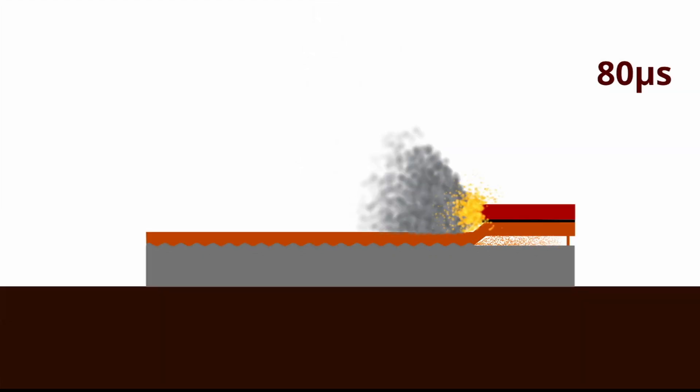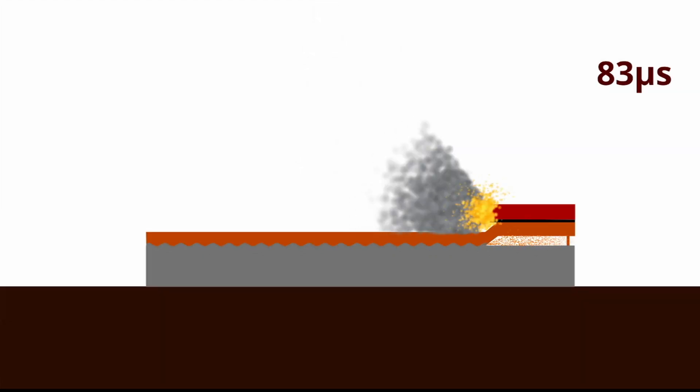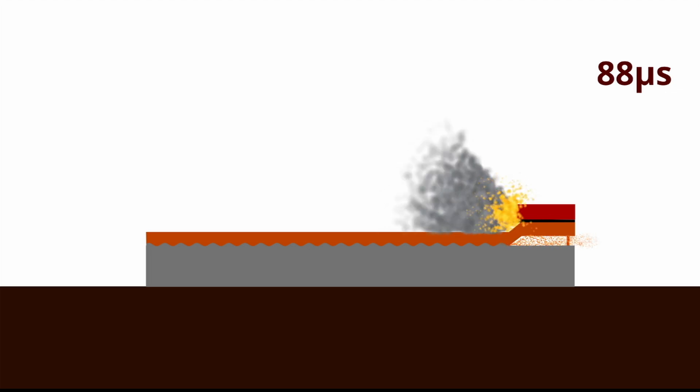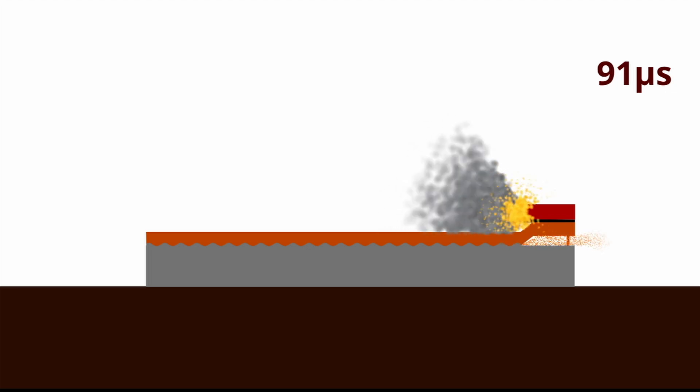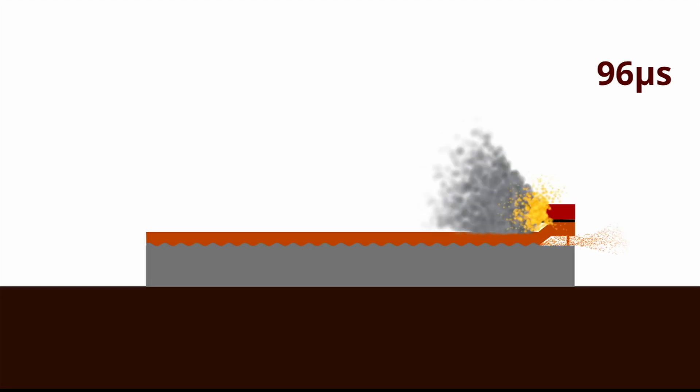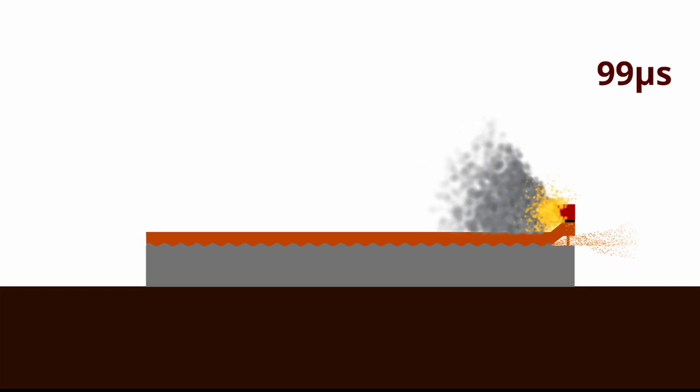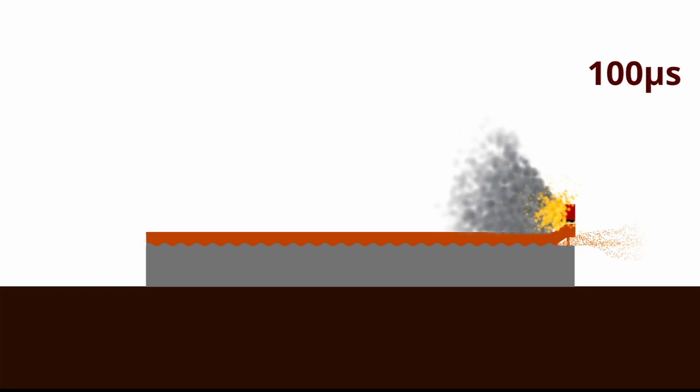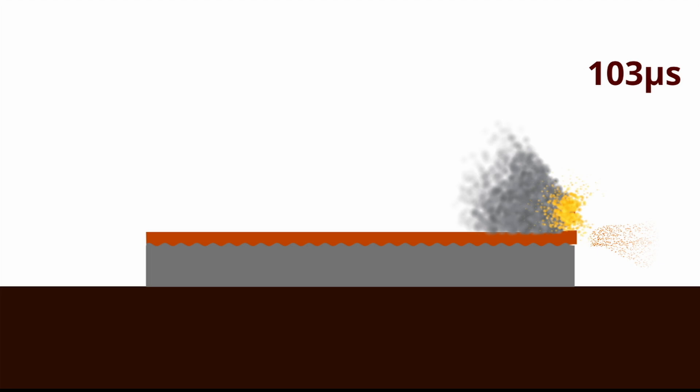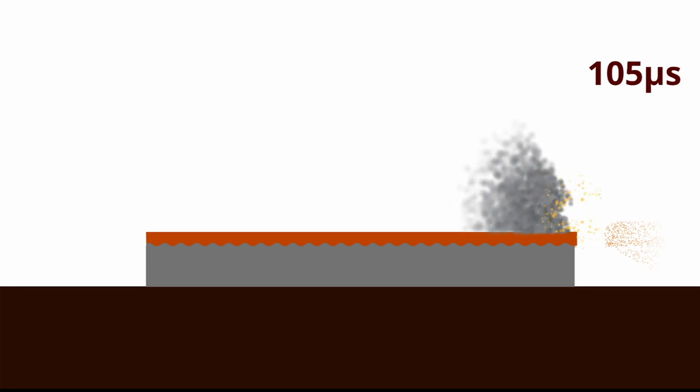As the explosive front moves forward, more of the flyer plate will be forced into the base plate. But this time the contact surfaces are conditioned for the impact to create a strong bond. The combination of the angled impact force and the force of the debris jet causes the newly formed bond to acquire a wavy shape.